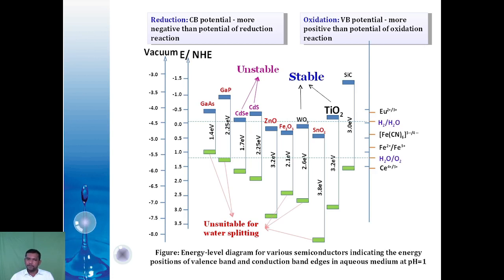Whereas in the case of titanium dioxide and tungsten oxide, the band gap is higher when compared to the chalcogenide materials. That is, the band gap of TiO2 is 3.2 electron volt, whereas for tungsten oxide it is 2.6 electron volt. Even though it has a higher band gap, it is found to be a stable candidate for water splitting. What we are doing is reduction as well as oxidation. Reduction occurs at the conduction band, that is, the conduction band potential is more negative than the potential of the reduction reaction. In the case of oxidation, oxidation occurs at the valence band, that is, the valence band potential is more positive than the potential of the oxidation reactions.